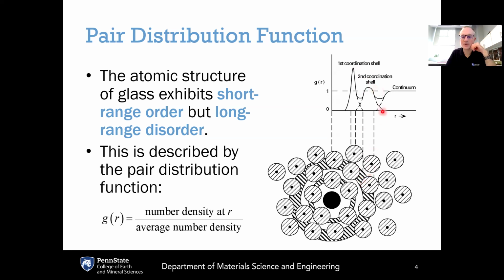Now, if you move on from the second nearest neighbor shell, there'll be another trough where you're less likely to find atoms. If you continue on, there might be a small peak for a third coordination shell, or it might just go to continuum where it asymptotically approaches 1. When this is approaching 1 or exhibiting some noise about 1, a pair distribution function of 1 means that the number density at that distance is approximately equal to the average number density. And the fact that this approaches 1 without any further peaks means that we don't have any strong correlations between the position of the central atom and the position of atoms at these long distances.